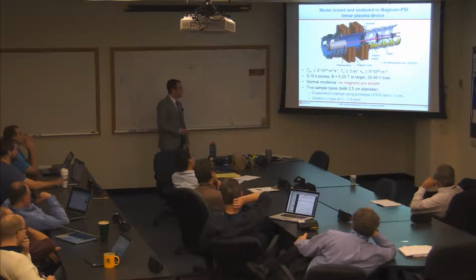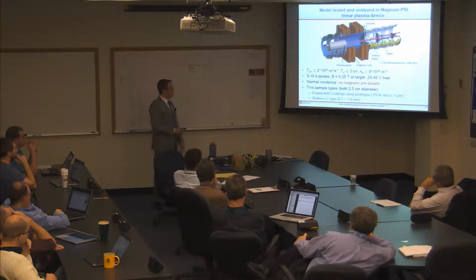This isn't actually what my targets looked like, but you can just think of this as an example. The experimental parameters were fluxes less than 2 times 10^24 per meter squared per second, less than 3 eV, less than about 10^21 per meter cubed. We typically ran 5 to 10 second pulses, which was mostly limited by the ohmic heating of the coils. This resulted in magnetic fields of about 1/4 Tesla at the target. We generally biased the target negatively at either -20 or -40 V to establish the kind of ion energies that you expect in the NSTX-U divertor. All the experiments I'm going to talk about were done at normal incidence, so normal magnetic incidence, so there was no magnetic presheath.